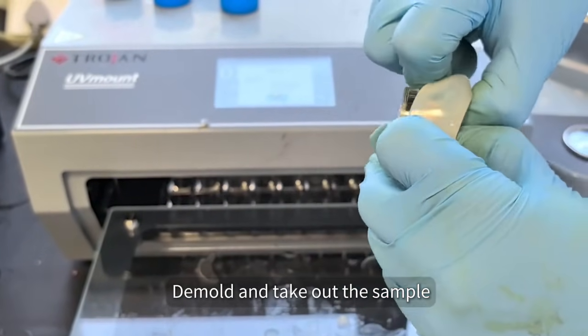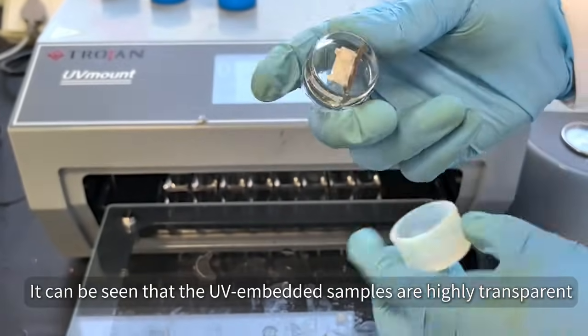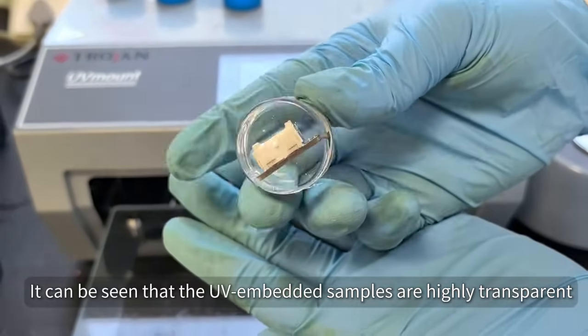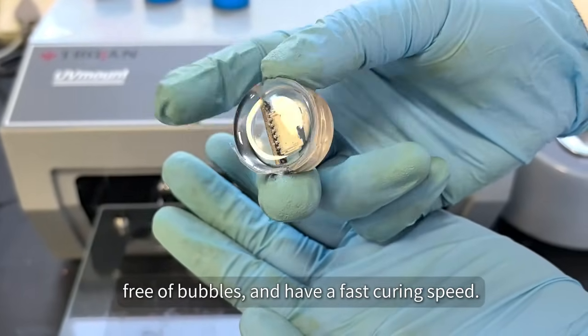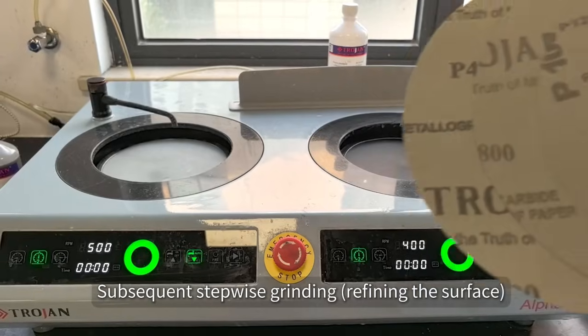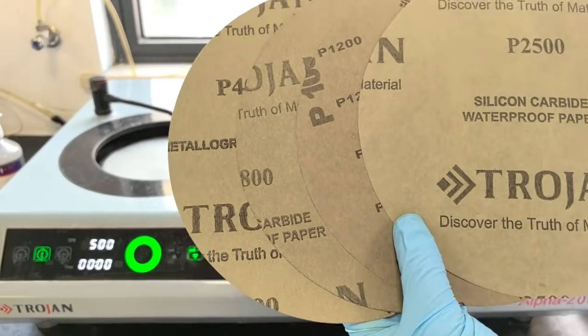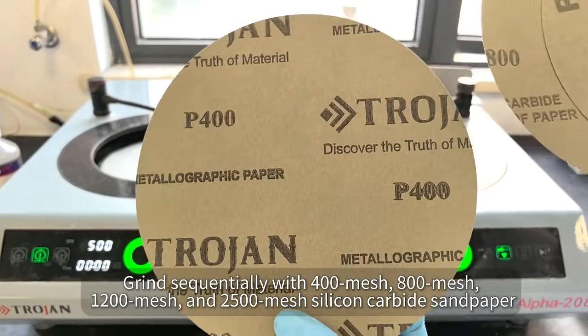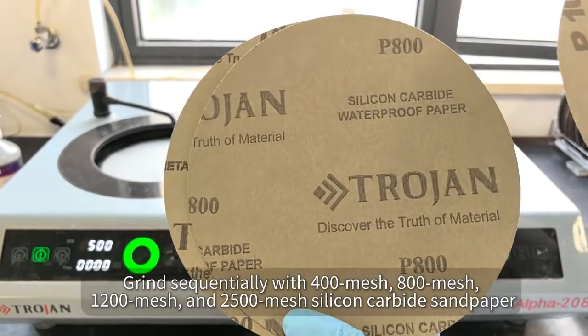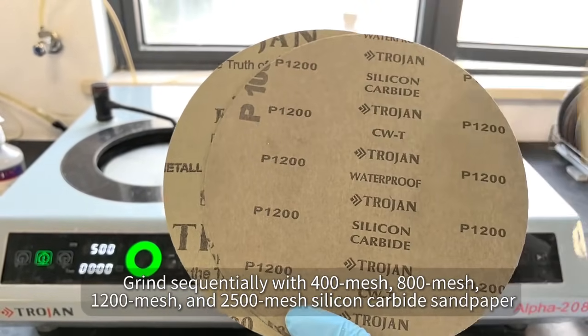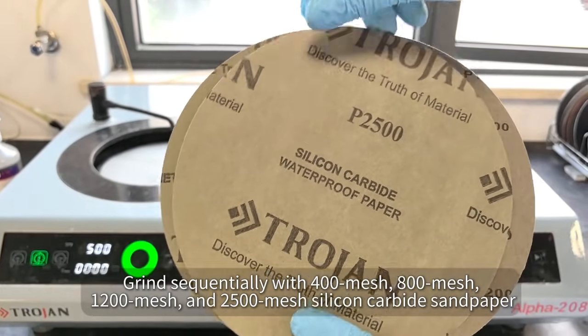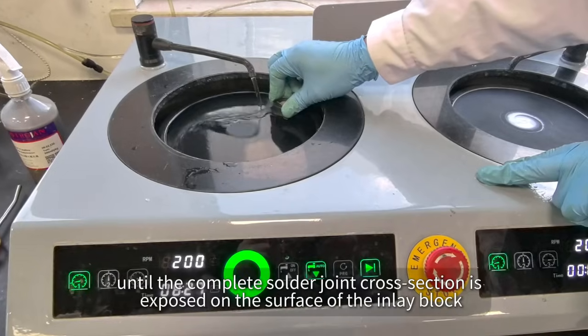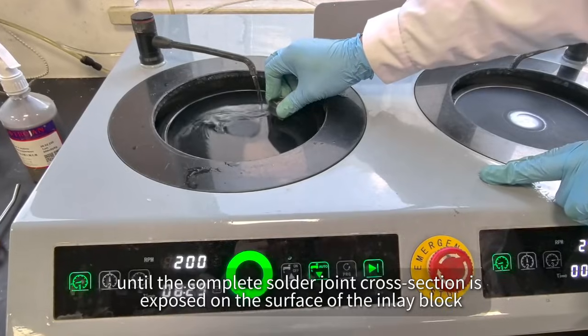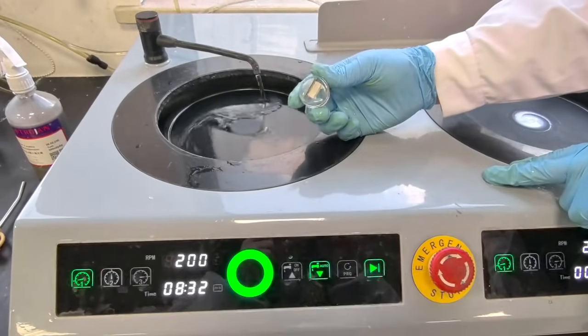Demold and take out the sample. It can be seen that the UV-embedded samples are highly transparent, free of bubbles, and have a fast curing speed. Subsequent stepwise grinding, refining the surface. Grind sequentially with 400 mesh, 800 mesh, 1200 mesh, and 2500 mesh silicon carbide sandpaper, until the complete solder joint cross-section is exposed on the surface of the inlay block.